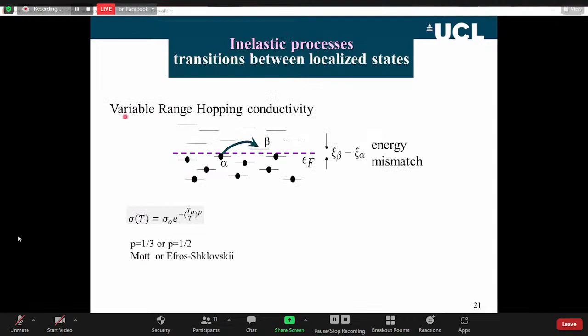This is the actual mechanism. When you have variable range hopping, the system is localized. In our case, we have a charge in a quantum well that sees the disorder caused by the tin segregation. And what happens is the transport is not by diffusion, but by hopping. An occupied state, with low chemical potential, finds a vacant state, alpha to beta, and hops. The carriers hop through the device, and it's a thermally activated process. This hop energy, this difference in energy between the states, is not a fixed quantity. That gives this additional power p. We don't seem to see that.